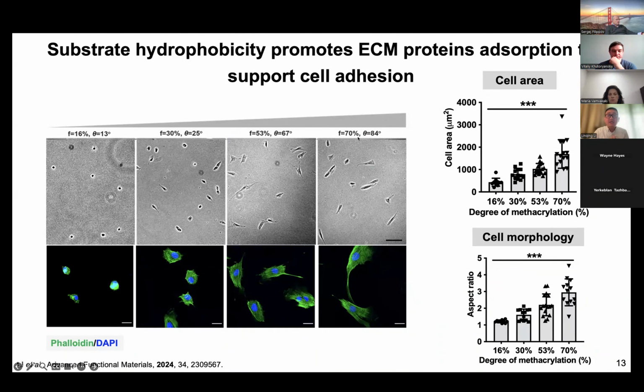at the highest functionality of the methacrylation and also the contact angle, you have more cells, not only more cells able to adhere to the surfaces, you apparently have larger cell spreading as well. So we quantify the cell area, and as you show there's a direct correlation as you increase the methacrylation, you also have a larger cell area as well as the aspect ratio, which is the length divided by the width of the cells, as higher aspect ratios indicate the cells are more elongated.